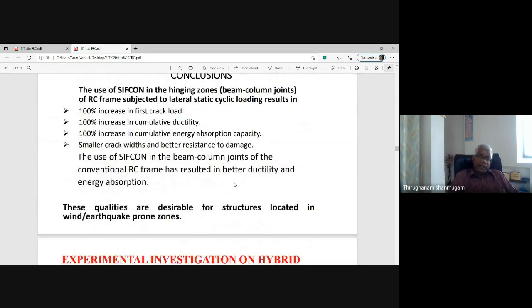Based on this experimental investigation on multi-bay, multi-story RC frames with SIFCON beam column joints subjected to seismic type loading, the following conclusions are drawn. The use of SIFCON in the hinging zones of beam column joints of RC frames subjected to lateral static cyclic loading results in a 100% increase in the first crack load, a 100% increase in cumulative ductility, and a 100% increase in cumulative energy absorption capacity, whereas the ultimate load is increased only marginally, say 20%.